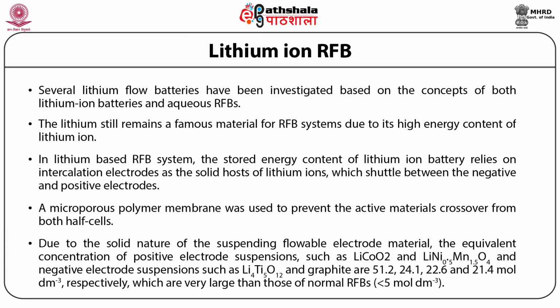24.1, 22.6 and 21.4 molar per dm cube respectively, which are very large than those of normal RFBs, which are less than 5 molar per dm cube. This provides the significant increase in the energy density, approximately 10 times than that of VRFB. The round-trip Coulombic and energy efficiencies of the lithium flow batteries using Li4Ti5O12 negative flowable electrode and LiCoO2 positive flowable electrode were reported to be 98% and 88% respectively.